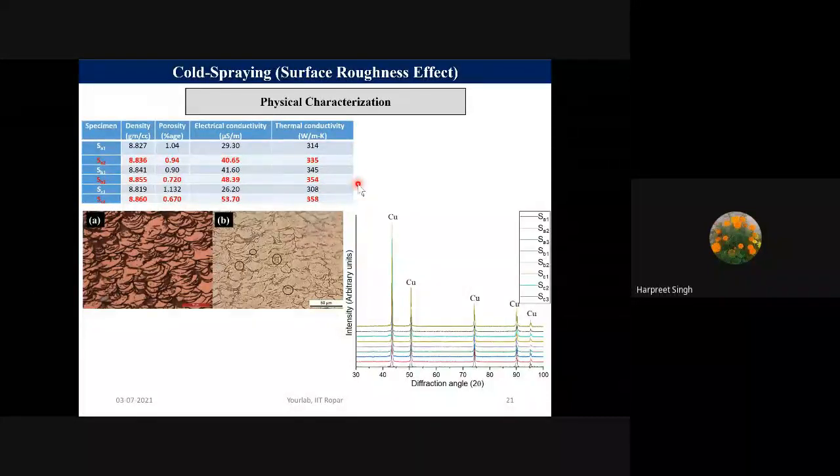As I said, we varied the surface roughness and produced 3 samples, and then we did their heat treatment also. That's what has been done here, right? So you can see this is as-sprayed coating, and this is heat treated. This is one sample which has been shown here. I don't know which one it belongs to, but you can see the merging of these splat boundaries.